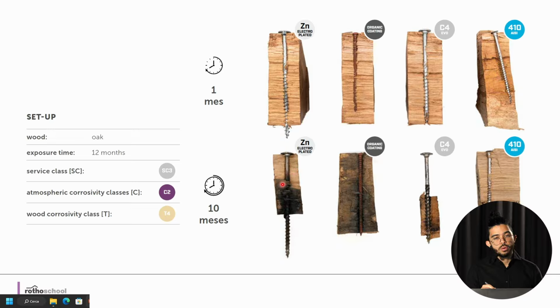So it's generalized corrosion, a critical condition in the entire screw. The organic coating behaved really well. You will see some stains of tannins, but the red rust is negligible here. So it was a very surprising result, very promising. C4 is a zinc-based coating, so we also knew that it would perform better than the zinc electroplated, but still there are some minor marks of red rust and a lot of tannins. So we know the C4 Evo would not be suitable for a service life duration.